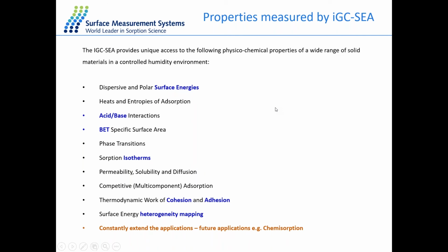So there's a few things that we can measure with IGC-SEA. One, the most common one is surface energy. And because we are injecting polar probes, we are able to understand acid-base interactions in terms of Ka and Kb. We are also able to understand and obtain isotherms, and as a result, we can then calculate the BET specific surface area. Other things we can measure are work of adhesion and cohesion, and also because we're able to inject multiple concentrations, we're also able to obtain a heterogeneity map of the surface of the sample.